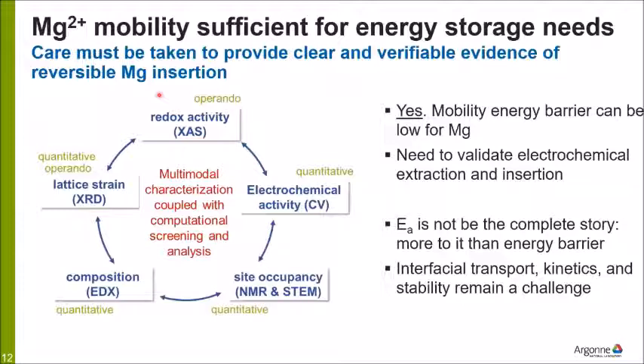quantitative, both in situ operando and ex situ characterization techniques that look to understand all of the redox activity on transition metal sites, lattice strain with removing and reinserting magnesium, and compositional changes to verify that indeed magnesium is present or removed. And finally, in the case of NMR and STEM, we verify even site occupancies and environment of the magnesium.